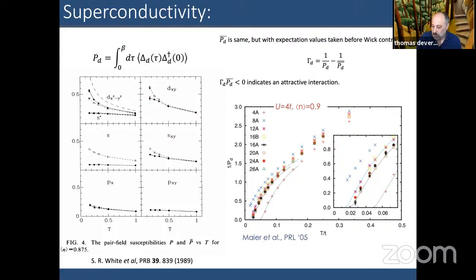And so this is very old work, which showed that D wave, dx squared minus y squared, is the dominant symmetry. And of course, this plot, I think, got us all very excited many years ago, which showed from DCA that as one changes the cluster size used in DCA for U equal to 4, 1 over the pair field susceptibility appears to hit 0 at a finite value of temperature on the order of 0.02 of the hopping T. So small values of T, but given T is on the order of a quarter of a volt or so, these are pretty decent numbers.